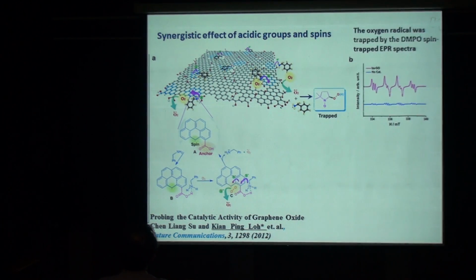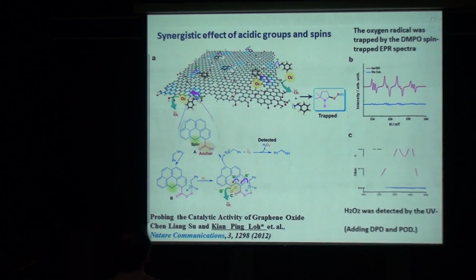So the synergistic effect of the acidic group and the spin is responsible for the catalytic reaction. We can follow this reaction using the DMPO spin trap EPR spectra. We introduce an oxygen molecule. The oxygen molecule is activated by this kind of dangling bonds and the carboxylic group structure. It's activated to form a superoxide, which can be trapped and detected as an EPR signal.